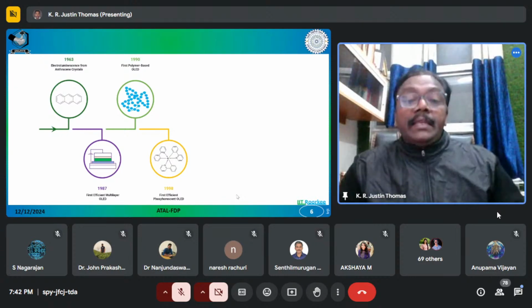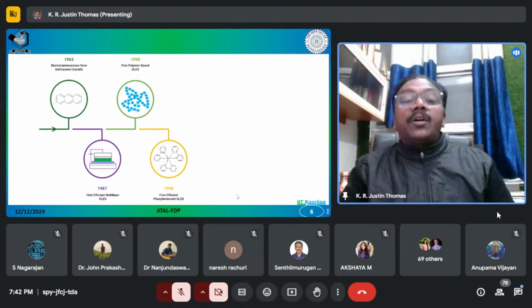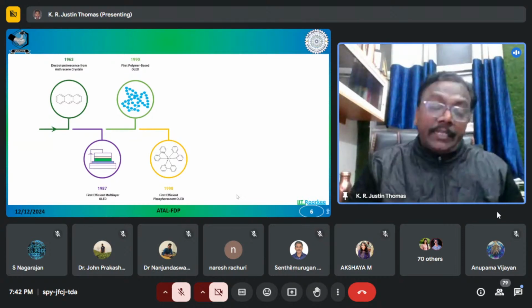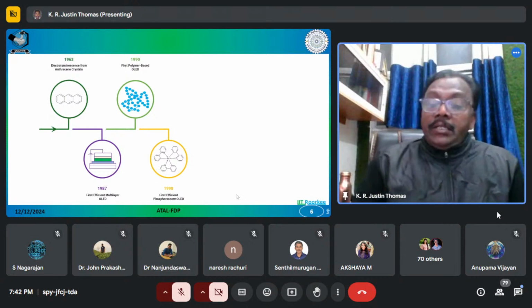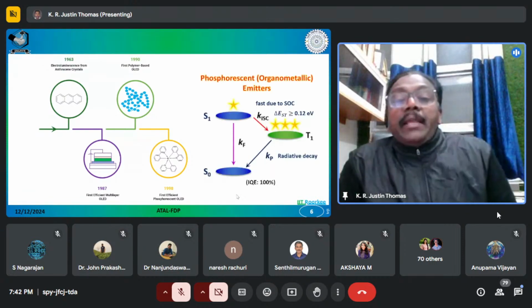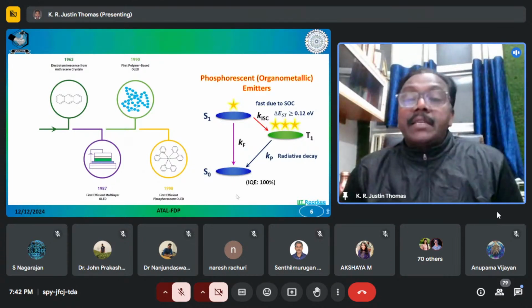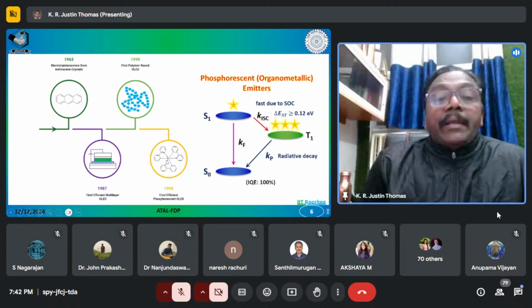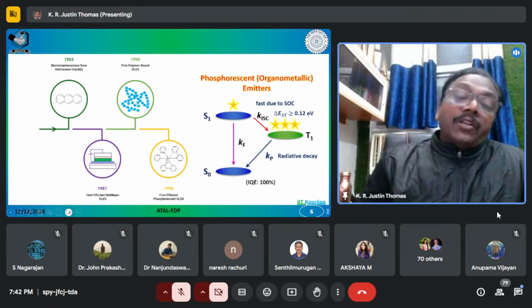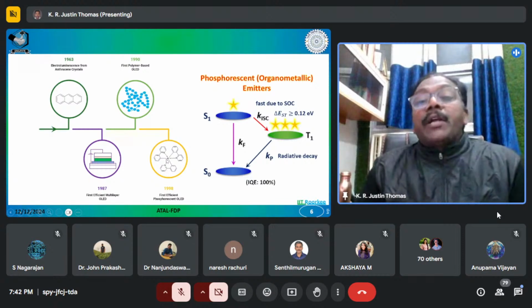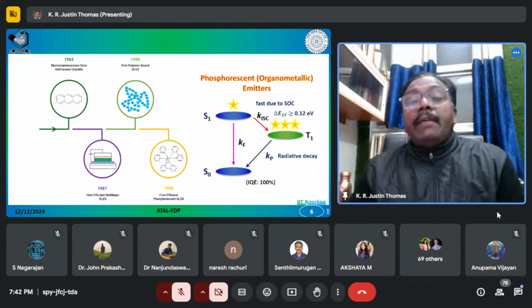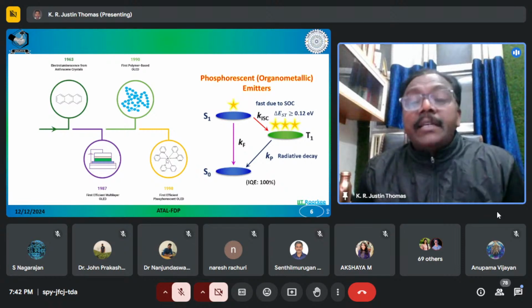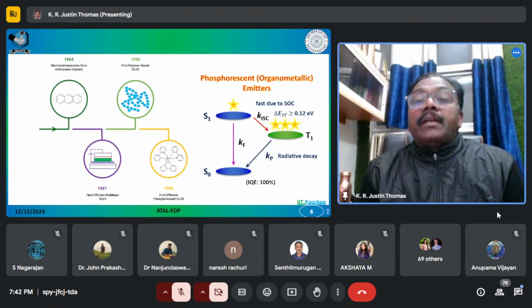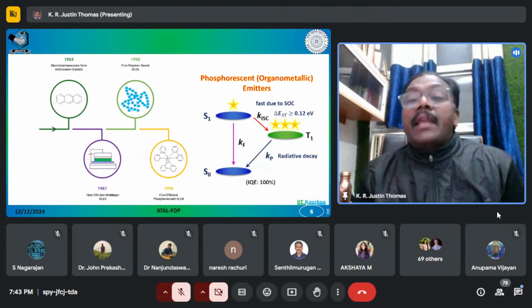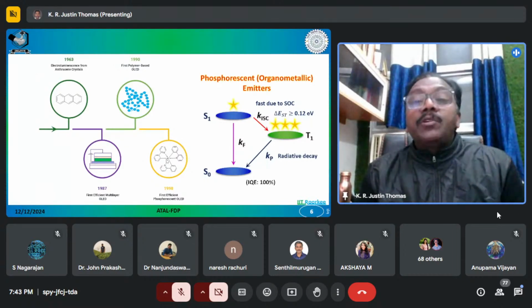That means in these kinds of devices, you are also harvesting the triplet exciton. That is the point here. Our physical chemistry clearly teaches us that when there is a heavy metal, in this case iridium, and you can also have ruthenium, platinum, and other metals, that heavy metal facilitates intersystem crossing. And in these kinds of organometallic compounds, generally the delta EST is slightly higher than 0.1 electron volt.